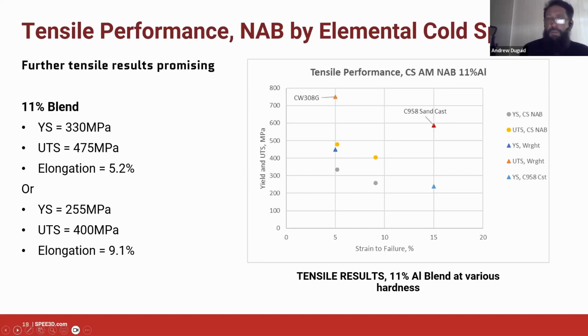Or you can go a little bit on the safer side and knock the yield stress down a bit, get a bit more elongation. And you're looking at an alloy that's got a yield stress that's comparable to the sandcast, or maybe a little bit above the sandcast value, not quite as ductile, but still enough ductility to be a serviceable engineering material. So that's really great. That's a good place to land. There's more work to do, but we're pretty happy with that. And we can see users for that material. But we might go on to the next slide.